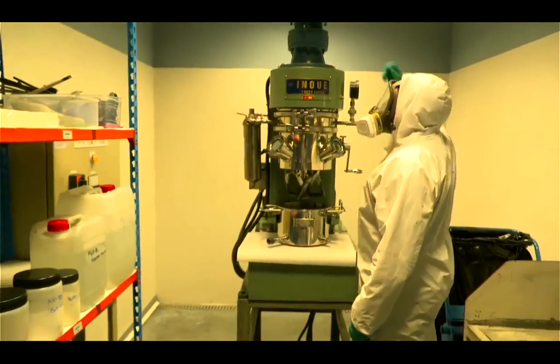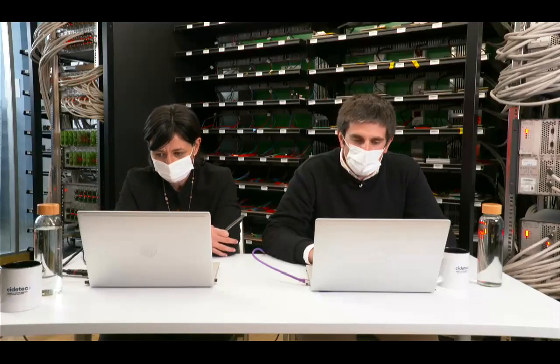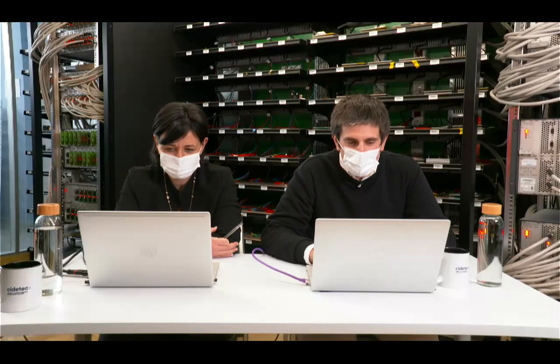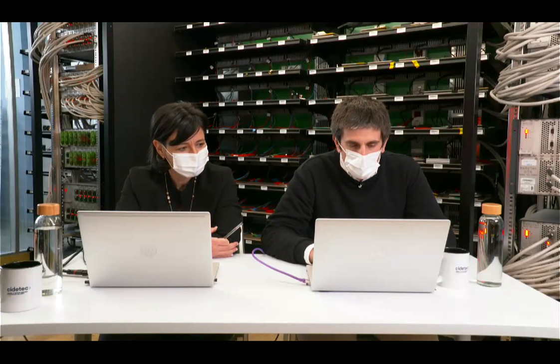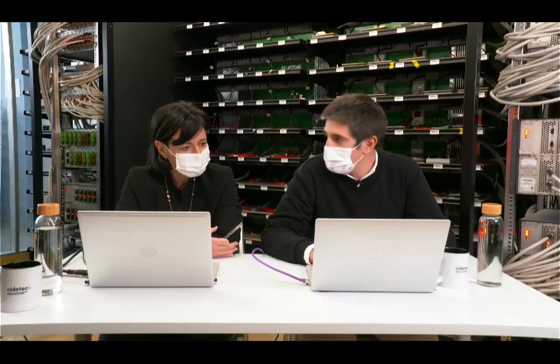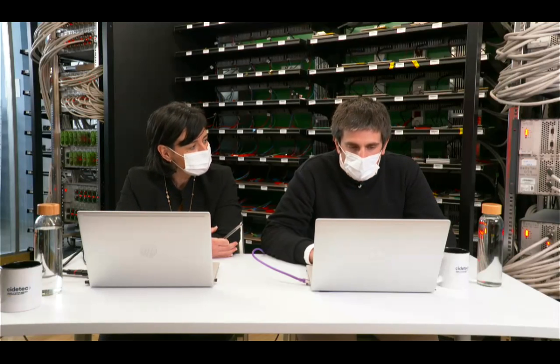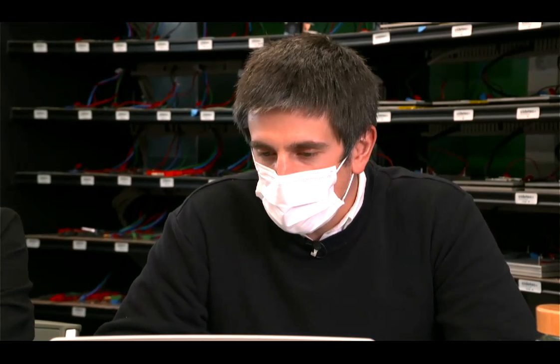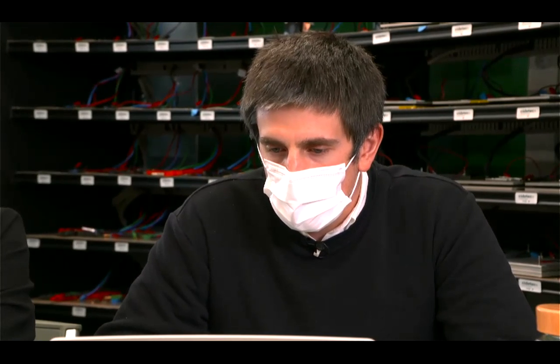Yeah. So we are changing again to calendaring. As we mentioned about the cathode calendaring of NMC and LFP, there's a question regarding whether it's true that the more calendared cathode is better. It depends on the requirements of the electrode that you want. It's true that for energy density, the higher the loading and the lower the thickness, if it works in the battery, you will have the best conditions for high energy.